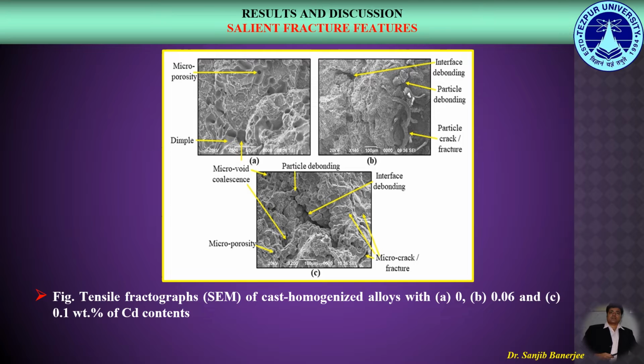Here we can see the tensile fractographs of the cast homogenized alloys with cadmium contents of 0, 0.06 and 0.1 weight%. Here we can see the evidence of microporosities, then the dimples which are the evidence of plastic deformation, then the interface debonding, that is the debonding of the surface from another surface, particle debonding, we can see over here the debonding of the particles from the matrix region, then the crack or fracture of the particle itself, then we can see over here the evidence of micro crack and fracture. As it is evident over here, we can see a micro crack, then we can see the coalescence of microvoids in many places. So these are the salient features which can be observed generally in the investigated alloys.